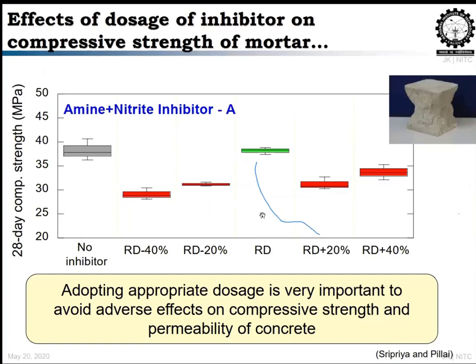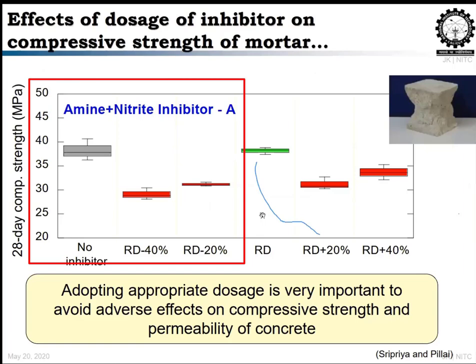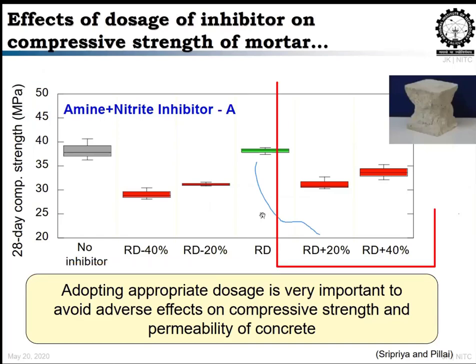And compressive strength is affected, not only the threshold level, if you are not properly choosing your dosage. Here it is a bipolar inhibitor, where the manufacturer has given a recommended dosage for a particular cement content, which we have followed, mentioned as RD, the recommended dose. The left side of the graph from RD shows dosages less than recommended, at -20 and -40, and the right of RD is +20 and +40 of the recommended. In the case of no inhibitor, at the left end, the strength is around 35 to 40, and at the recommended dosage we again get almost similar strength. But if you reduce or increase the dosage, you get less strength. So choosing a dosage to achieve appropriate strength and also durability is the concern.